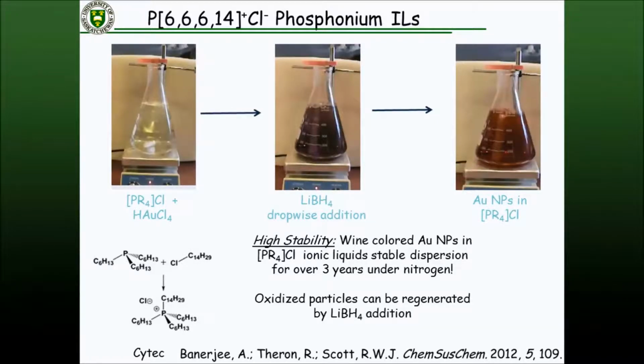So we started with this. The system we started with was a 66614. So 3 hexyl groups and a C14 group on every phosphonium center. Add the gold chloride salt, add lithium borohydride as reducing agent to get the gold nanoparticles in the ionic liquid.